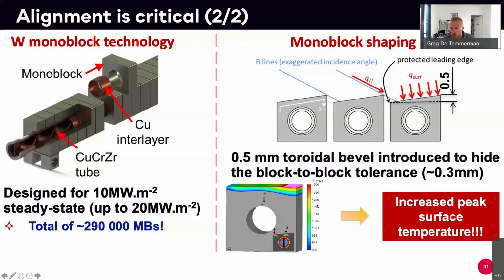Now, you pay a price, because when you tilt those things, you can see it here, part of the surface will not be wetted by the plasma anymore. So you reduce the area on which you can deposit the power, which means you drive the temperature up. And typically you see that we can get up to 1300 degrees in normal operation, and you have a very strong thermal gradient also. For two reasons: you are using a square block and a round tube, so you naturally have more cooling in the center than at the edge. But because you tilt, you have more power on this area than in this area, so you also drive another thermal gradient.